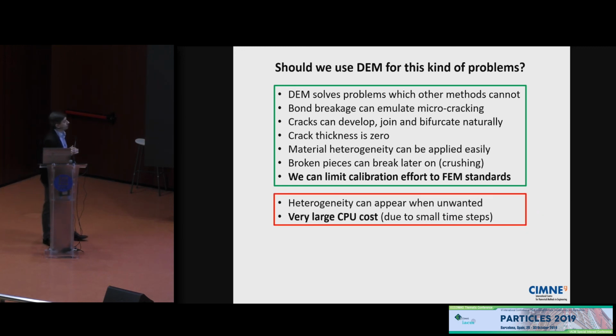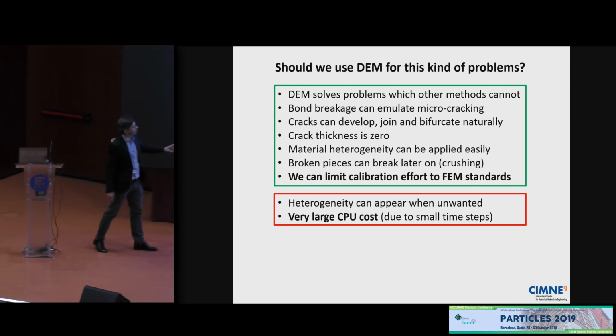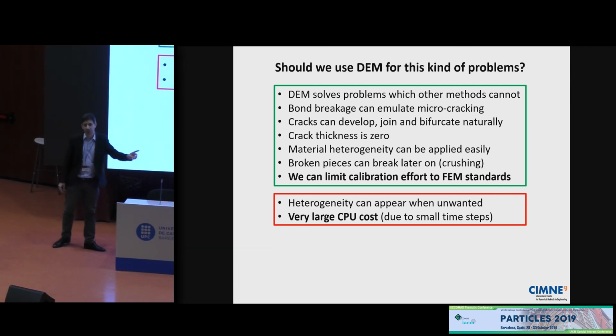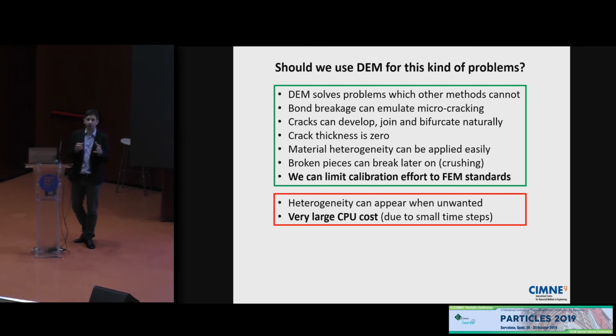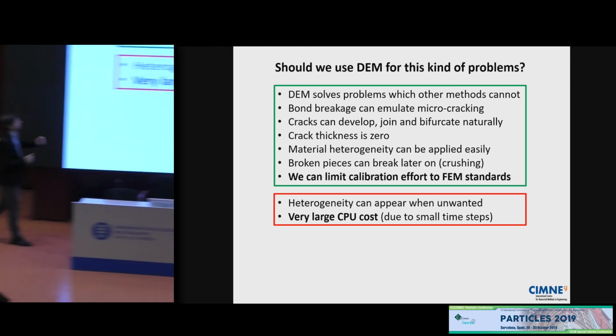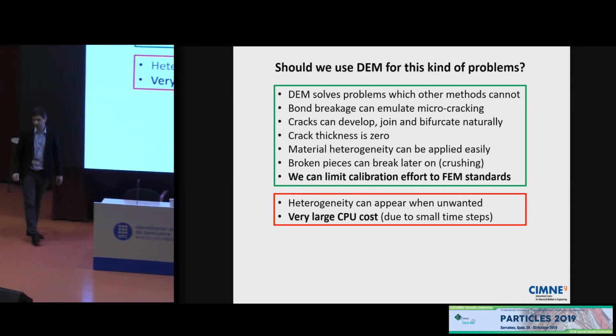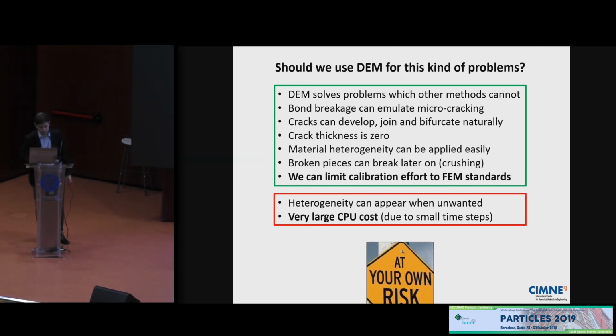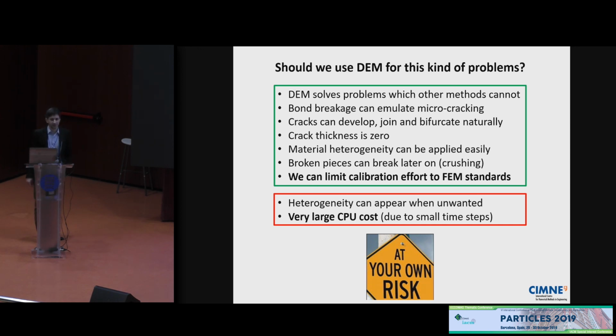On the other hand, we have the problem with the heterogeneity that can appear when unwanted, because the packings can be very random. They have defects, they have pores, they have voids, and also a very large CPU cost. Not due to a big number of particles, which is true as well and can be solved with supercomputers, but the problem that we are facing most commonly is the small time step. We have very rigid materials, we have very small particles, and the time step is getting really small. So for us, this is the worst problem of the DEM. The rest, we are very happy with that. So use at your own risk. And that's all.